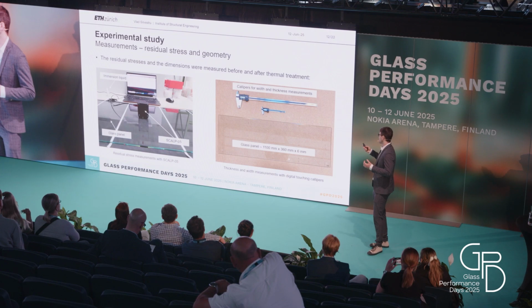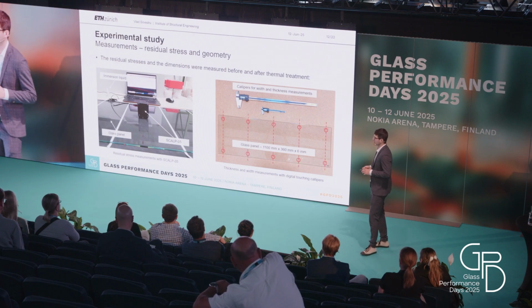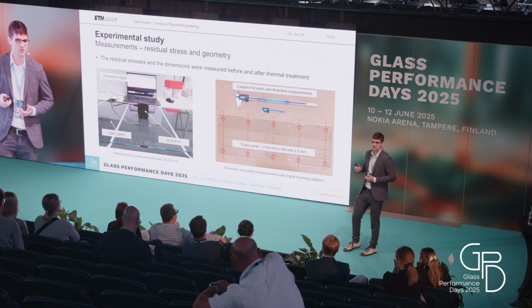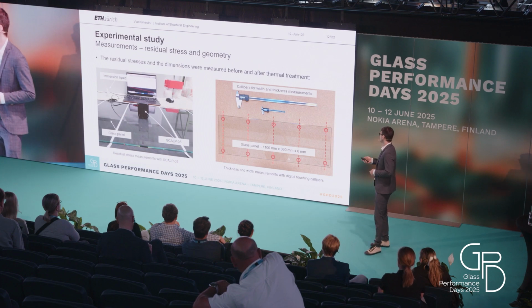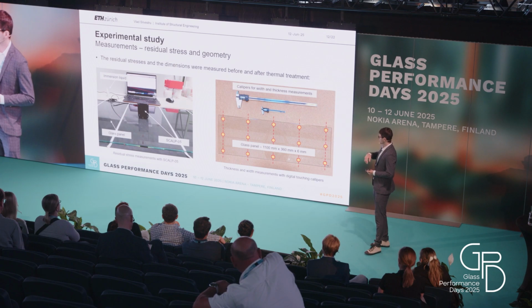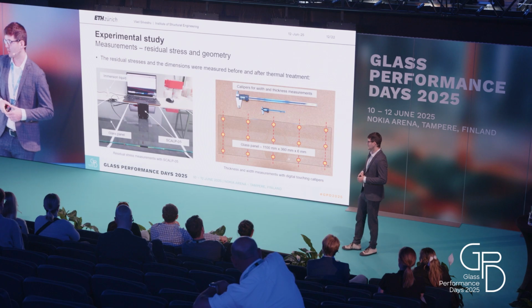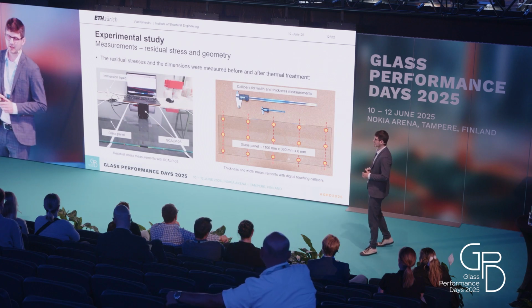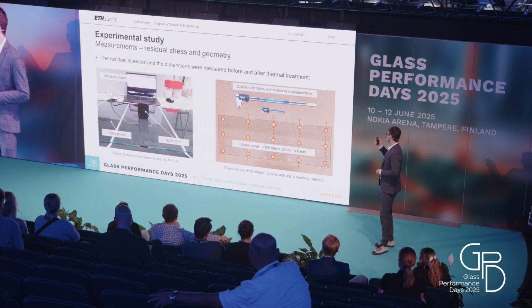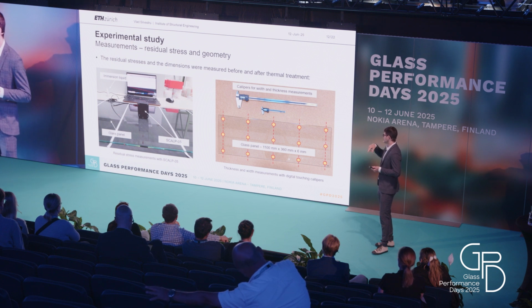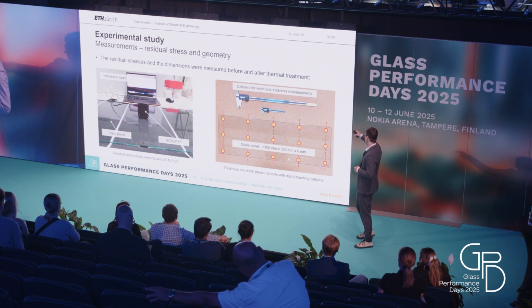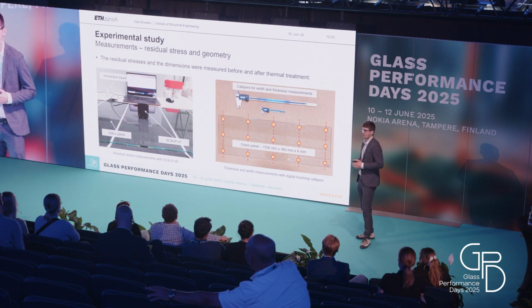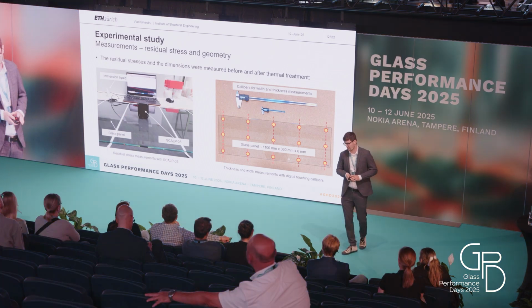The measurement of residual stresses we did with a caliper. We also measured the geometry at different points, but we didn't notice any change at the temperatures that we used here. For the residual stresses, we measured on both surfaces, so both the top and the bottom surfaces. We also didn't detect large differences there. For some samples, we also measured in different directions, so X and Y, but since we were quite far from the edge with the measurement points, the differences were not very large.